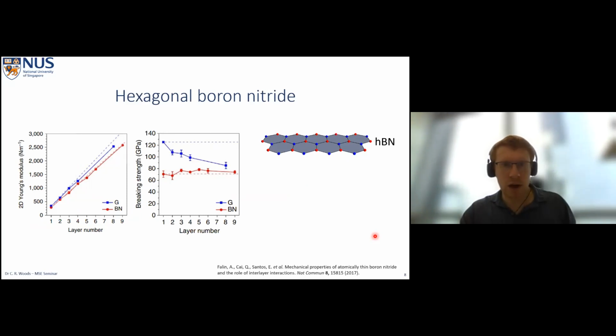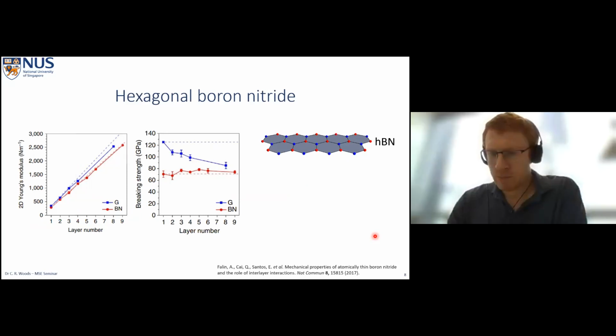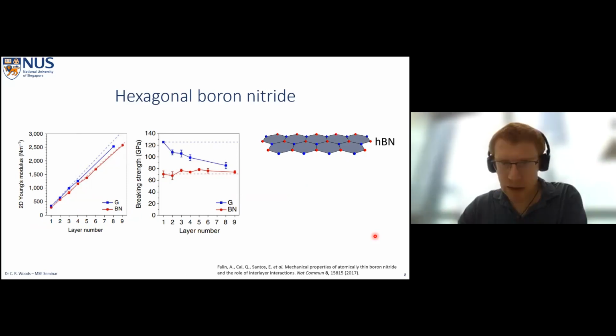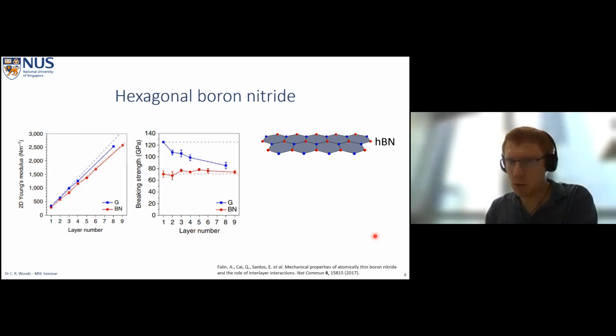It shares close to carbon's strength, and it has a Young's modulus, which reduces as we move down to few atomic layers. But as we do that, we also increase the breaking stress as all these materials follow Griffith's law. So if we reduce the size of our dimensions, the breaking stress should increase. So this is a nice convergence of 2 material parameters. As we go to 2 dimensions, they become easier to stretch, but they should also be able to stretch further before they break. So this is going to be useful for our piezoelectricity.